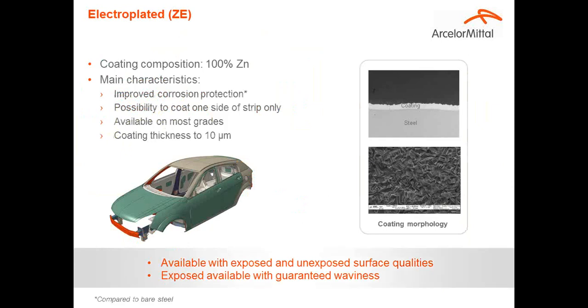Electroplated coating, as presented already in the processes, is a pure zinc coating, which is applied by electroplating and brings an improved corrosion protection compared to bare steel. It is a coating which we can decide to apply only on one face, so it is available in mono-face. It's available on most of our grades, and the coating thickness can be up to 10 microns. This coating is available for both exposed and unexposed surface qualities, and it's also available, if the customer wishes, with a guaranteed waviness. We will see a little bit later exactly what waviness is.